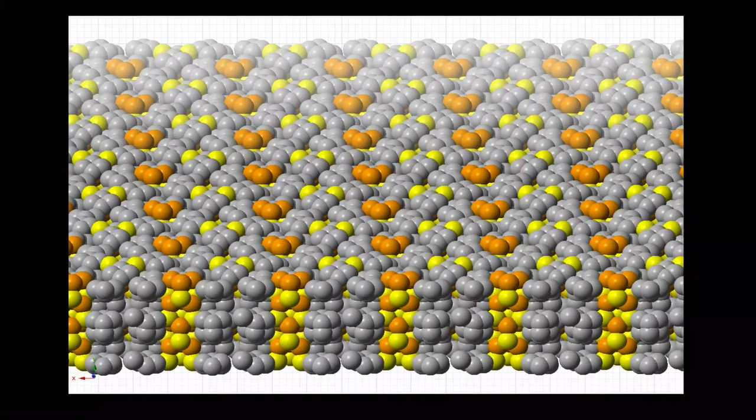That brings up the next image. This is a really interesting one showing the plane of many wires. The wires would actually be going vertically up and down in the solid, surrounded by this diamondoid shell. The interesting thing here is that this is a solid material — a crystal you can hold in your hand — and yet inside of it are millions of tiny nanowires that are just three atoms in cross-section. The wires are parallel to each other, so they don't transmit electricity from one to the other, but they're all carrying electricity separately. Their unusual properties are due to their small size and isolation.